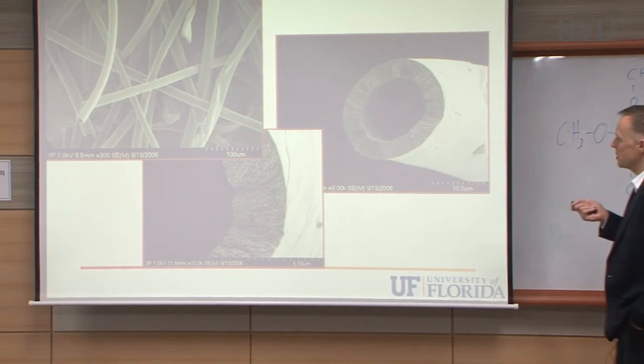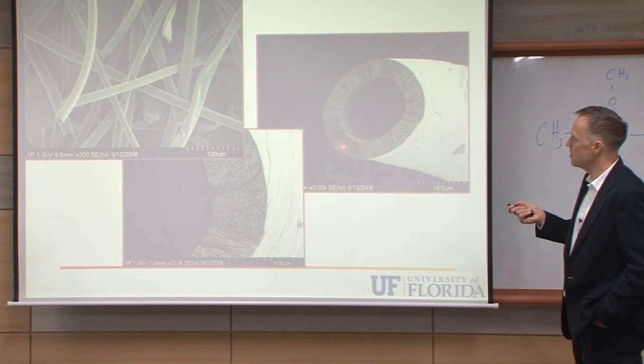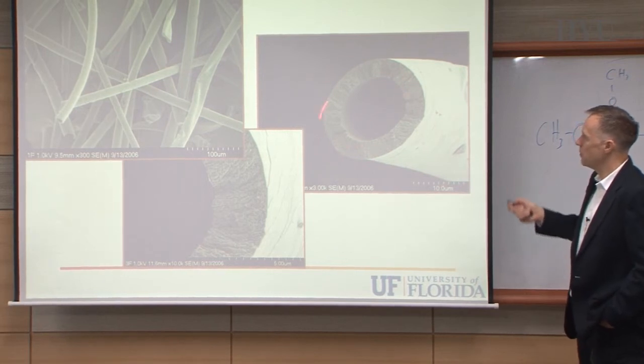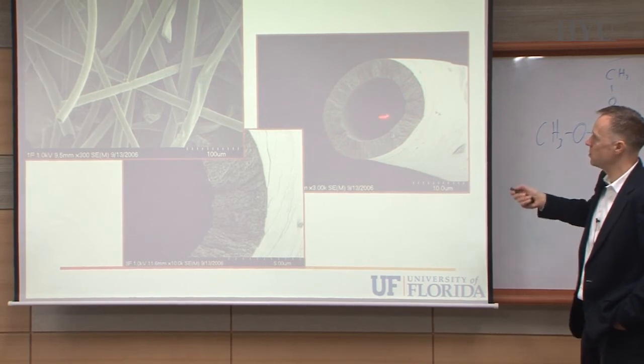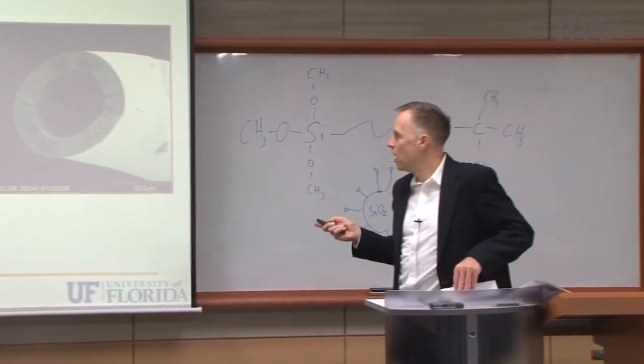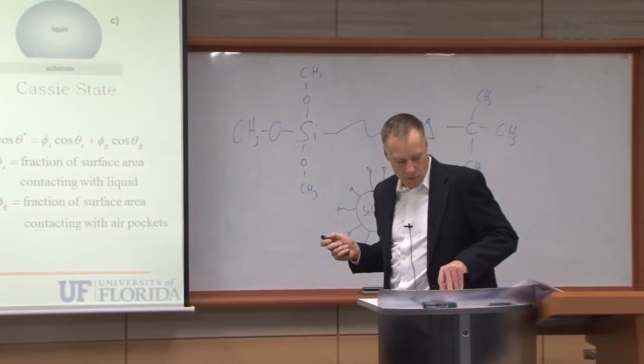And what you can do by this then is the fibers are much larger, of course. You see it's in about the 20 microns thickness, but now you have porosity in the fibers, and because of the chemical reactions happening, it dries from the outside to the inside. You start to form a hollow inside in the system.